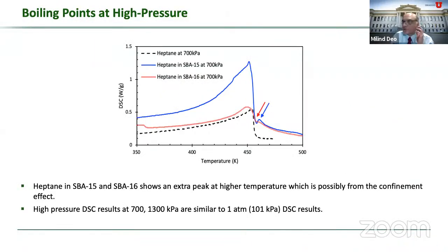The second part of the story is somewhat incomplete. So we're also looking at boiling point transition using DSC. We were able to confirm some of the things that Sinton's group saw, which is that we were able to see the so-called confinement peak well above the bulk peak in a high pressure, high temperature differential scanning calorimeter. We have two of them, one that goes to low temperatures and high pressure, one that goes to high temperature and high pressure.